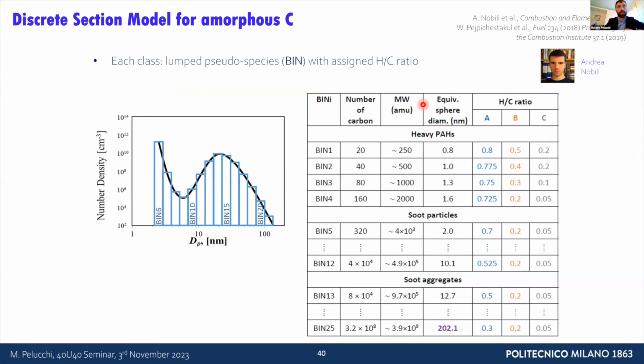Everybody's probably familiar with the discrete section approach to soot modeling. Of course we cannot pretend we are tracking each single particle, so taking the particle size distribution function, we define pseudospecies that we call bins. We then assign an H to C ratio that varies to stand for the soot maturity. We use a uniform spacing factor of 2, so we go from 20 carbon number in 25 pseudospecies up to 10 to the 8 carbon numbers, which stands for a spherical equivalent particle of 200 nanometers.